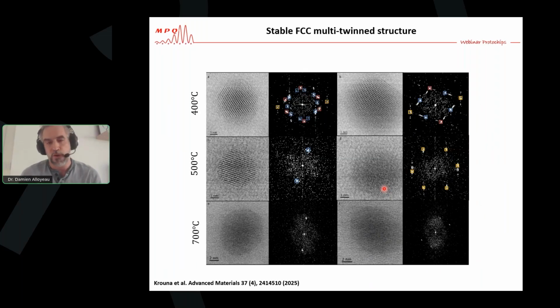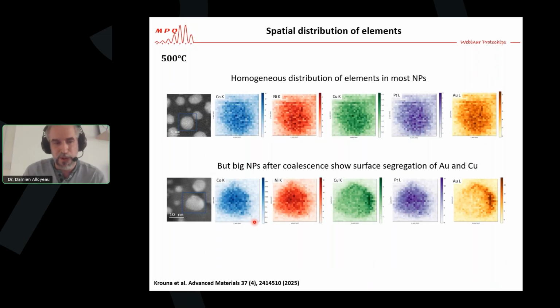Of course, if you want to know more, you need to work at higher resolutions. So we also studied these nanoparticles during this experiment at high temperature with high resolution. The images are fantastic. It shows the stability of the sample holder, but at the end, not much change regarding the structure. From 25 to 700 degrees, particles remain in their FCC structures, monocrystalline or polycrystalline. It's more interesting to study the spatial distribution of elements. We realize that in the nanoparticles that did not coalesce, you have a homogeneous distribution of all the elements in the nanoparticles. But in the particles that have coalesced, the big particles that you see here, where we saw this different contrast area within the nanoparticles, with EDX we prove that in fact we have a segregation of gold and copper at the surface of the nanoparticles. So gold and copper want to go to the surface, and it's accelerated by coalescence.